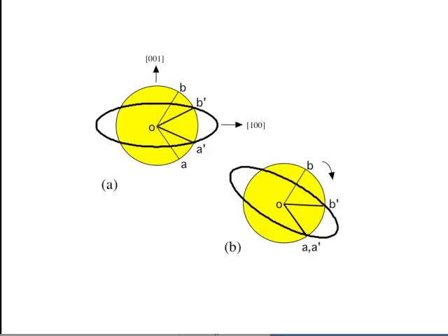Okay? Right. So supposing now I take that ellipsoid and I give it a rigid body rotation, so that one of these lines comes into coincidence, the other one goes further out, then I recover an invariant line. Okay? So the Bain strain combined with a rigid body rotation gives me the necessary line which makes martensitic transformation possible. There's no way I can pick two lines to come into coincidence. So we still have the inconsistency with the observed shape deformation. But the rigid body rotation that I add to the Bain strain exactly predicts the observed irrational orientation relationship.